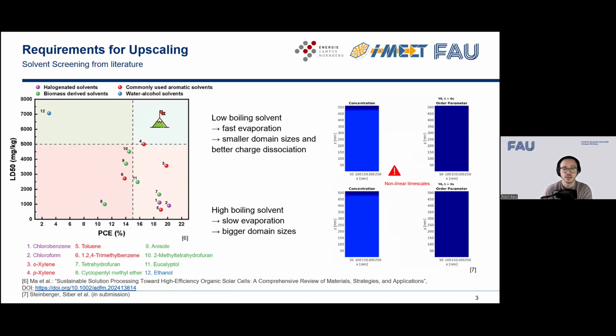On the left-hand side, you can see a chart of what efficiencies we can expect from which solvent, according to literature. Of course, for different active layer systems, but those are mainly champion efficiencies, and how toxic they are. LD is lethal dose. It's a rough estimate that tells you how toxic a material is. One of the most used solvents in literature is chloroform. As you can see, it's very toxic compared to others, but it also gives great efficiencies. For us personally, the optimum trade-off is with o-xylene, because the efficiencies are comparably similar to chloroform. However, the toxicity is a lot less. So that's quite important to us.